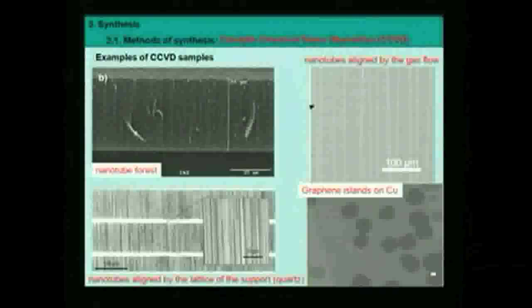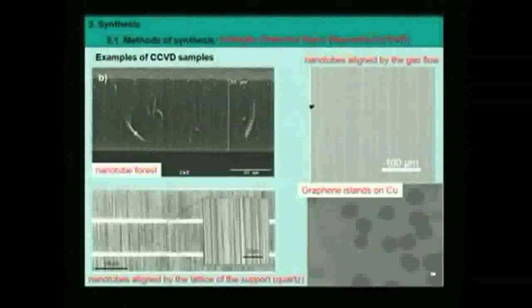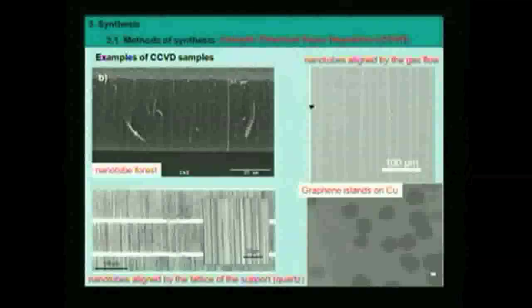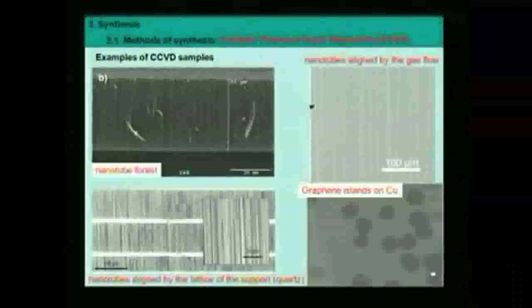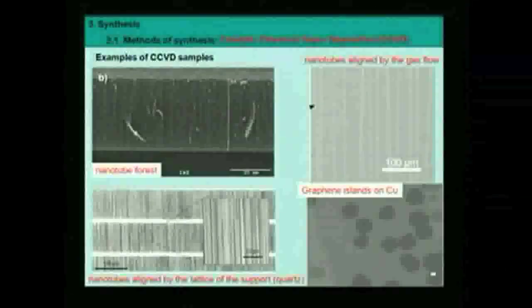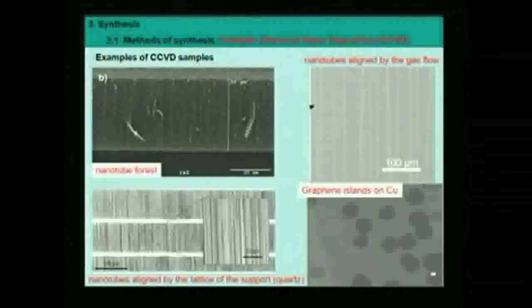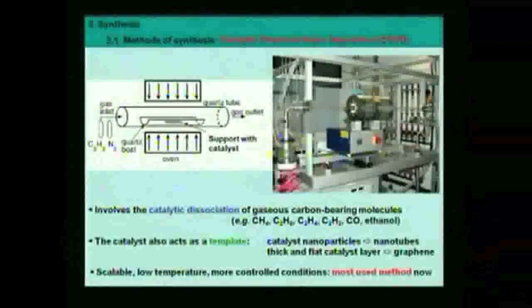So this is an example of what you can get, a nanotube forest, with tubes growing perpendicular to the substrate, to the support. Another example is the growth of nanotubes parallel to the substrate. The first example is this. You see nanotubes, and just below in the background is the support, which is usually also silicon oxide or silicon. Here you see that the nanotubes are very well aligned, and they are also quite long, several hundreds of microns. The nanotubes in this case were aligned by the gas flow used inside the reactor.